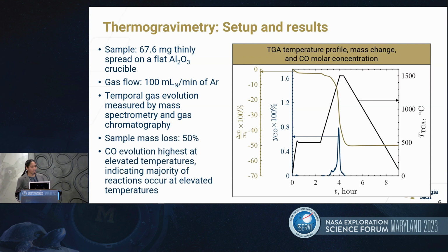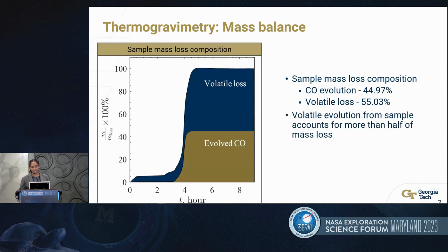As shown in the gold line, the sample lost about 50% of its mass, which coincided with CO evolution shown in the blue line. The temporal CO evolution showed that the majority of these reactions were occurring at elevated temperatures. Looking at the mass balance, about 45% of mass loss was due to CO evolution, and about 55% was due to volatiles leaving the sample. This means that more than half of the mass loss was due to volatile evolution.